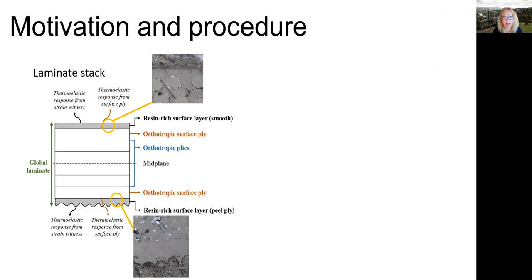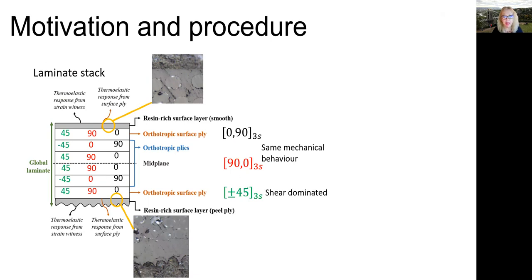To examine the adiabatic response and heat transfer characteristics in composite materials, we used three different laminate configurations: a 0,90 and a 90,0 stack which have the same mechanical behavior but different thermal properties, and a plus minus 45 degree stack which is shear dominated.